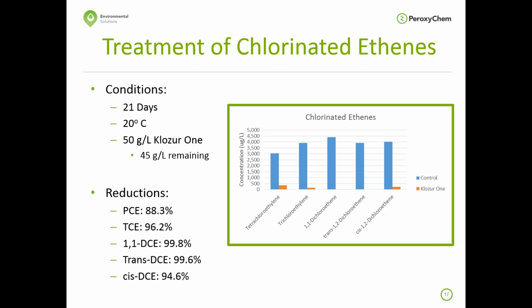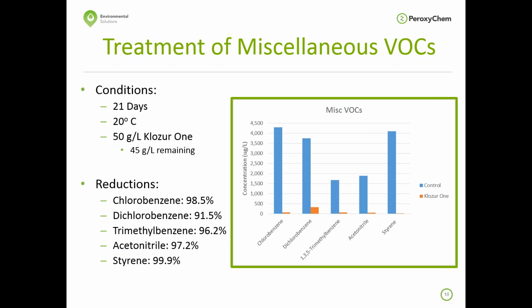Moving on to your chlorinated ethenes, same test conditions. PCE was degraded by 88% in this study. We've seen it degraded by even more in other studies, but this particular study, it was 88%. TCE by 96%. The different DCEs were degraded by anywhere from 94.6% up to 99.8% with 1,1 DCE. Finally, looking at a few different miscellaneous VOCs, monochlorobenzene was degraded under the same test conditions by 98.5%. Dichlorobenzene was degraded by 91.5%. 1,3,5-trimethylbenzene was degraded by 96.2%. Acetonitrile was degraded by 97.2%, and styrene was degraded by 99.9% in these studies.